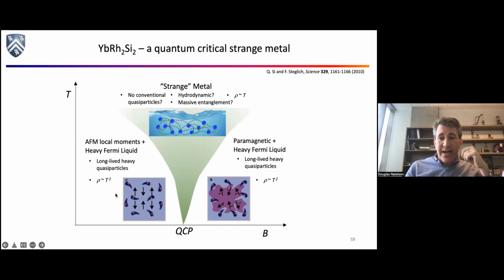And these F electrons end up talking to the conduction electrons, and you end up with very flat, comparatively flat bands. And this is another way of saying that the effective mass of the charge carriers in the system acts like they're really heavy, like hundreds of times more massive than free electrons. That just means that if you vary their momentum, their kinetic energy doesn't go up very much. Okay. And this material in particular, at low magnetic fields, the magnetic moment of those F electrons is ordered antiferromagnetically. They form a pattern, up, down, up, down, up, down, up, down. Okay. But it's a Fermi liquid. So the resistivity goes like T squared.